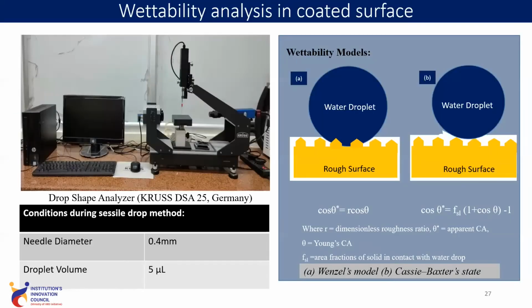Wettability and tribological properties of the coating. Wettability basically determines the ability of the liquid to wet the surface. Wettability is determined by measuring the contact angle. Contact angle is measured in the drop shape analyzer. This is the needle diameter and droplet volume that we are using. Wettability is determined by using two models.